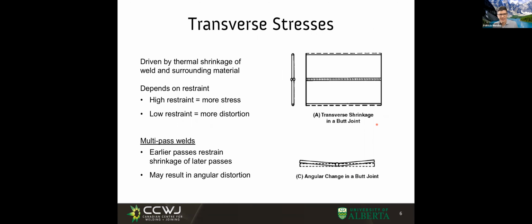So about transverse, and this is using welds, there is something interesting: as the plate gets locally hot, it expands, and then when it cools down, it shrinks. So if I have no restraints, the plate is going to move out and in as it needs, and we might end up with higher distortions. On the other hand, we can clamp really well. If you look at the Lincoln Procedure Handbook, it has a whole subsection just on clamping. And you clamp it really well, so when it wants to expand or contract, it can't. Good news is it's not going to be too distorted. Bad news is it's going to have a whole lot of stresses accumulated, right? So that's about transverse shrinkage.